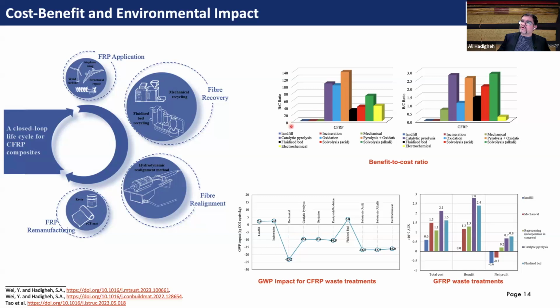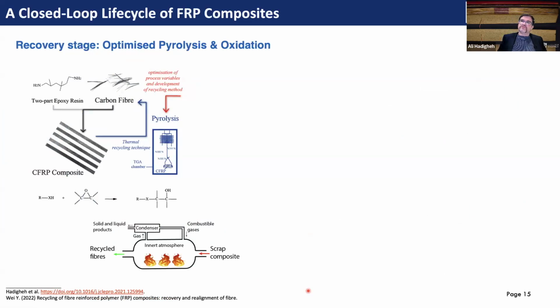We looked at cost benefit to cost ratio, and also global warming potential of different methods, including landfill, incineration, mechanical, catalytic pyrolysis, solvolysis, and so on. Amongst these, for the type of our FRP composites, we started with pyrolysis and oxidation method. If you are not familiar with those methods, pyrolysis is basically pyrolyzing or burning your samples within an inert atmosphere, in this case nitrogen, and then extracting fiber and separating fiber from epoxy within that system. And then also reusing those epoxies as combustible gases or byproducts after the process.